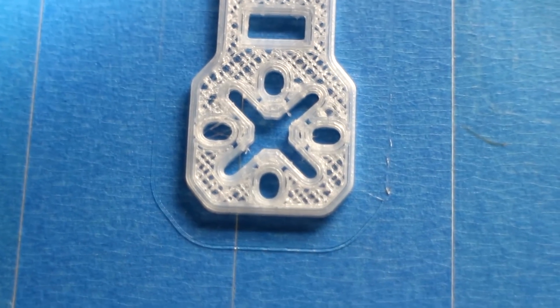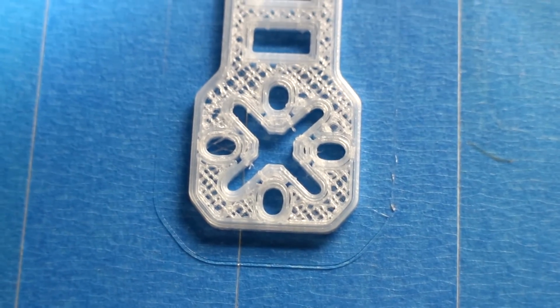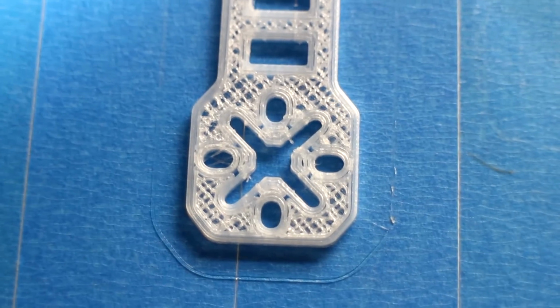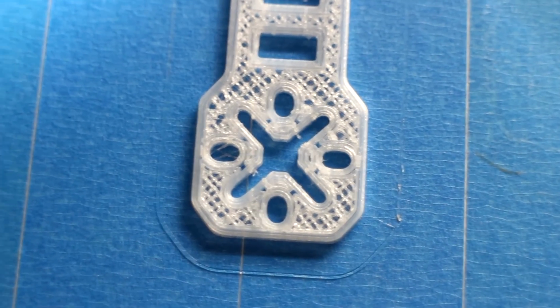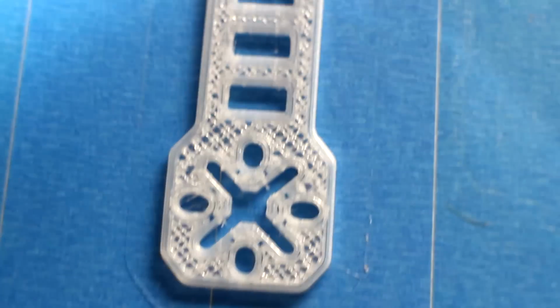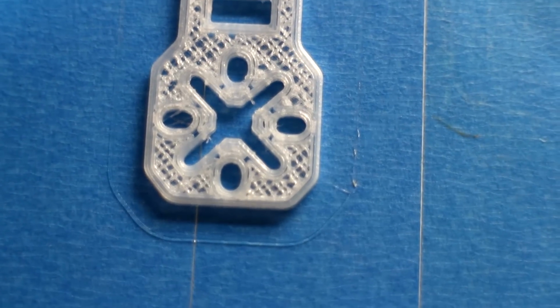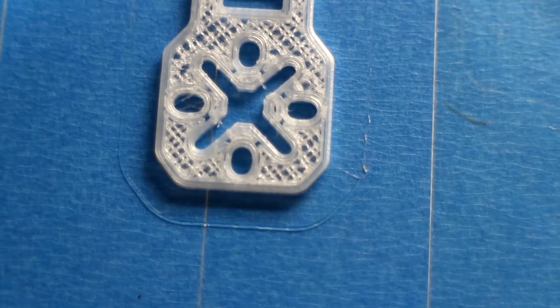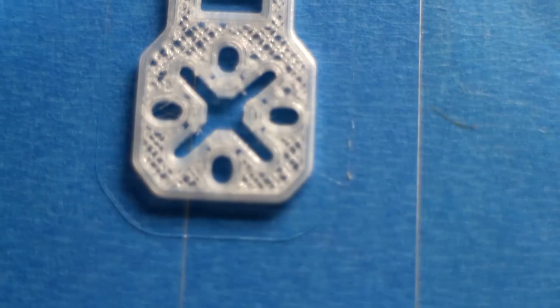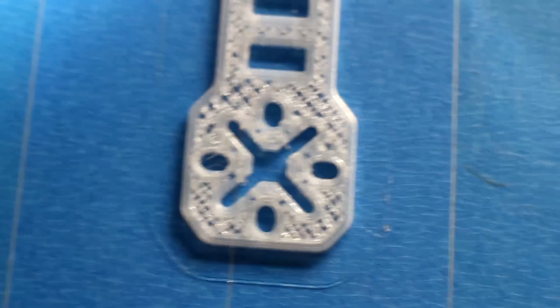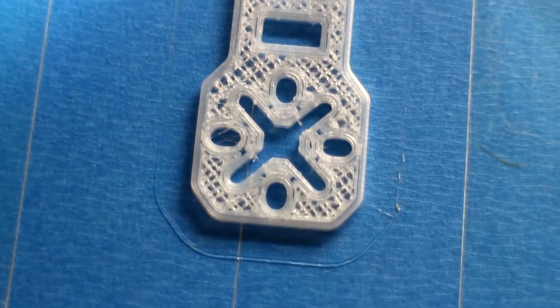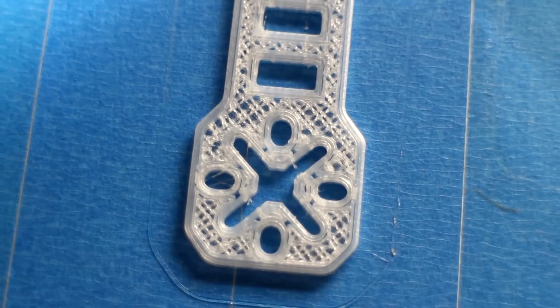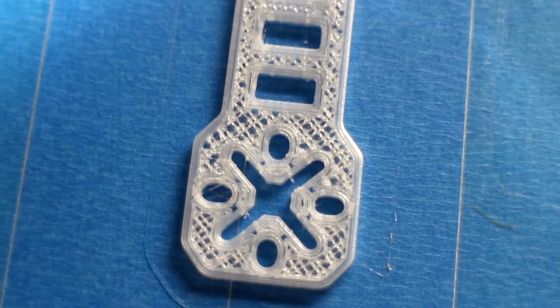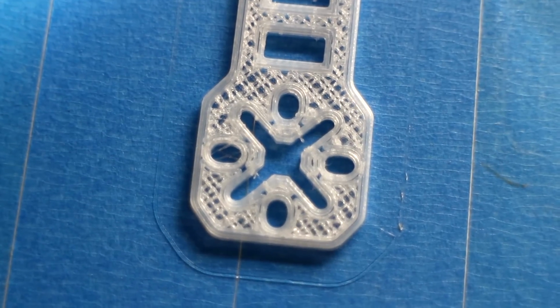Unfortunately, I've had to stop this print halfway through because I realized when I sliced this part with Slic3r, I left the default extrusion width at zero. And for some reason with the newer version of Slic3r, it seems to want to extrude with gaps in between some of the perimeters and between the perimeters and the infill and so on. So that's going to affect the strength of this part. So I think I'll just cut my losses here and I'll start this one again after I've sliced it properly.